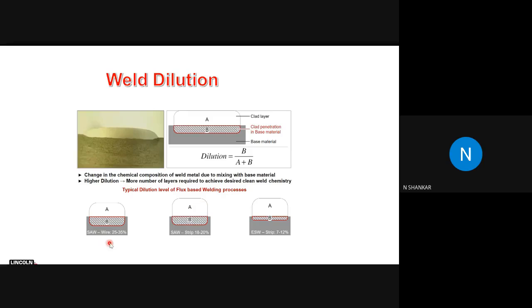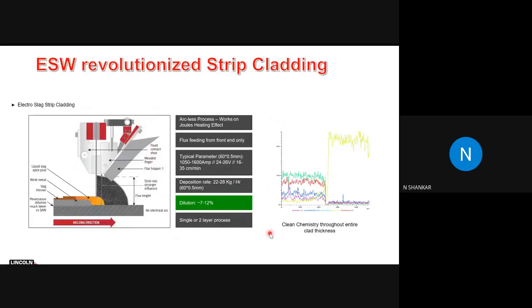In submerged arc, when you do it with wire, you're able to get 25 to 35% dilution. When you do it with strip, you're able to get 18 to 20% dilution. And when you go to electroslag welding, you are able to get 7 to 12% dilution. So it's better to go from submerged arc strip cladding, or SASC, to electroslag strip cladding, or ESSC. The electroslag strip cladding revolutionized things basically because it was able to achieve a much lesser dilution of 7 to 12%.